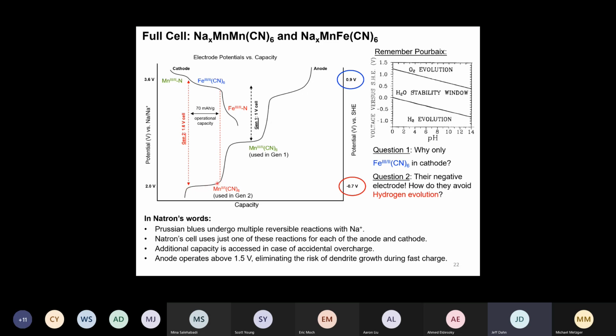So, folks, when you look at that, do you think the mean field theory would fit that curve fairly well? And the answer is yes. And why would it work fairly well? What's the sodium-sodium distance in this stuff? Does anybody know, based on the structural parameters Michael gave us before? It is very large, so the repulsive interaction is very small. Right. It's about 5 angstroms between sodiums, roughly.